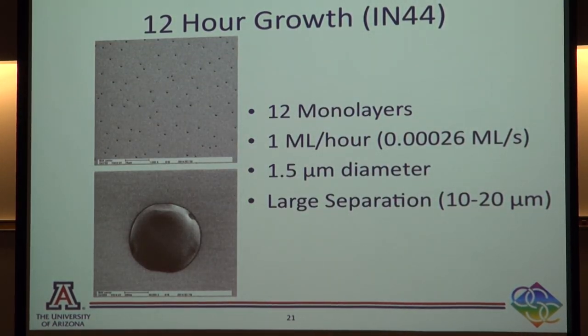So this was one of our biggest samples. What's also interesting here is that you start having a rather large separation between the indium islands, about 10 to 20 microns between them. People at Riber were laughing that it almost could be another measure of how clean our surface is, because effectively you have an indium atom traveling 20 microns to find another one to stick to. But that's what you get when you give a machine to crazy people.